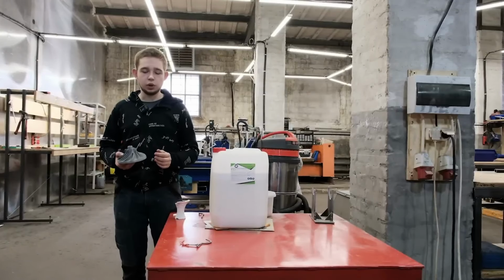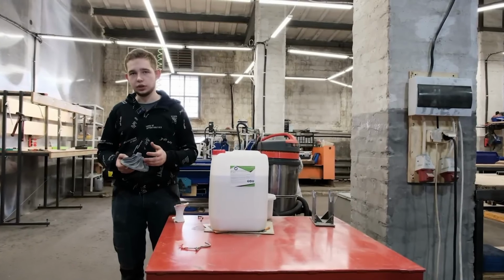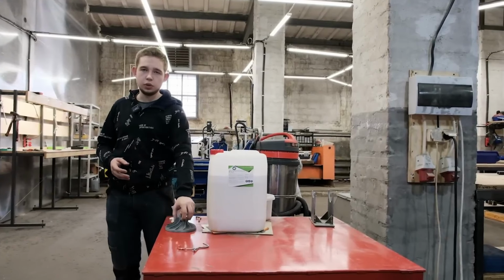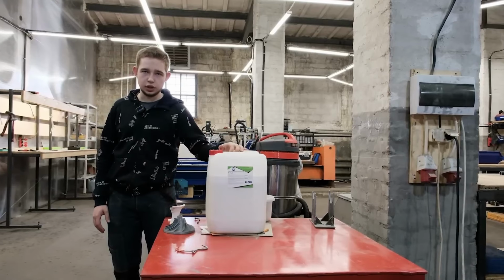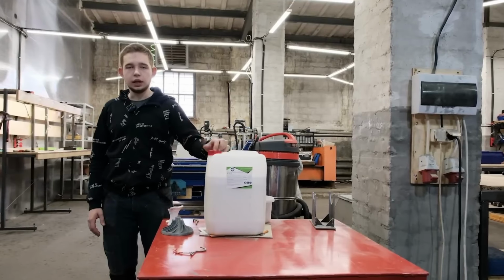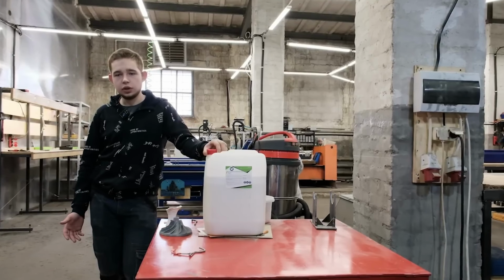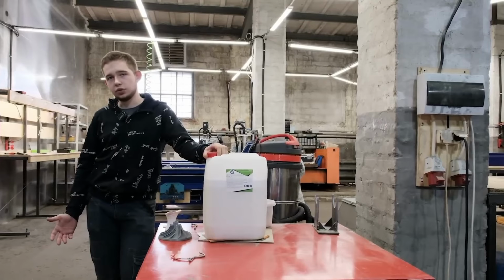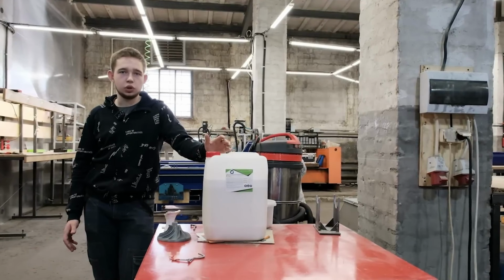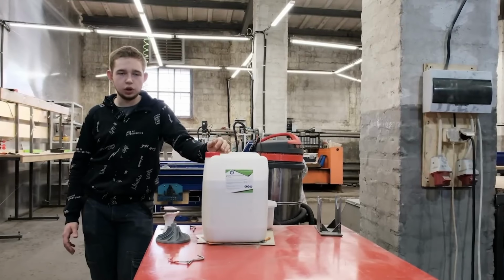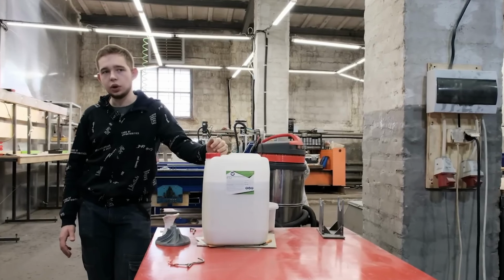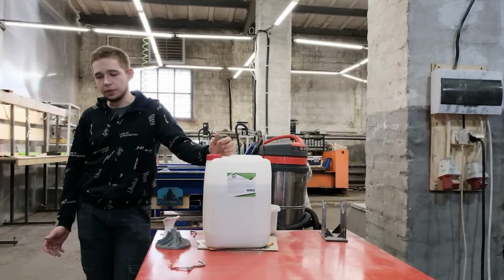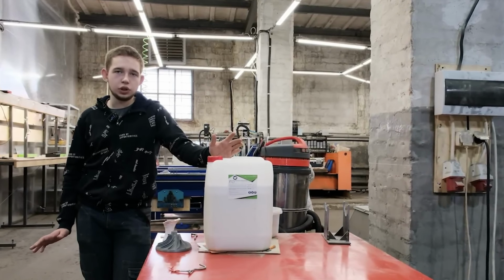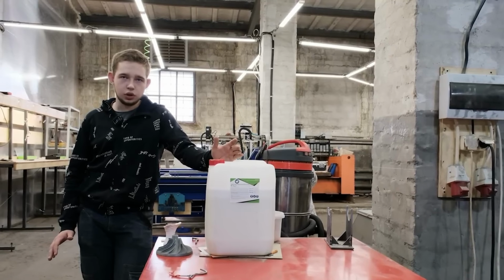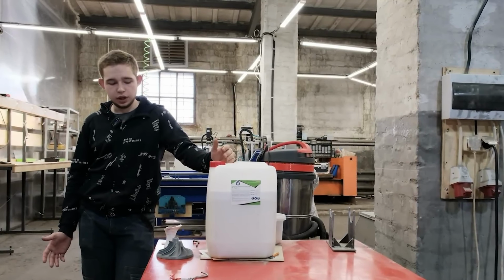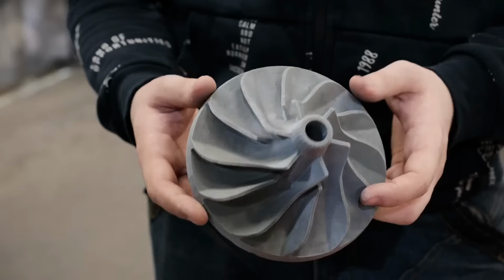The next stage of the process, following the creation of the wax or burnout model, is to carefully prepare a slurry mixture from a binder and a filler. The filler is made up of extremely fine-grained refractory materials, typically around F1200. As a filler, you can use electrocorundum, which is aluminum oxide, or marshallite, which is silicon oxide, or other refractory materials. On average, approximately 2 kilograms of filler material are needed per kilogram of binder solution to prepare the slurry.